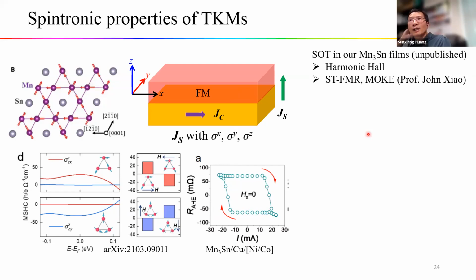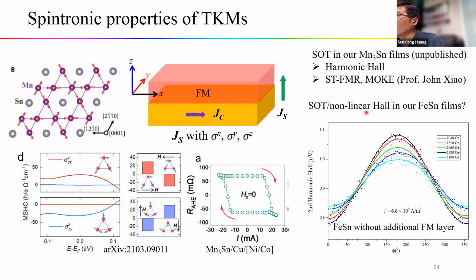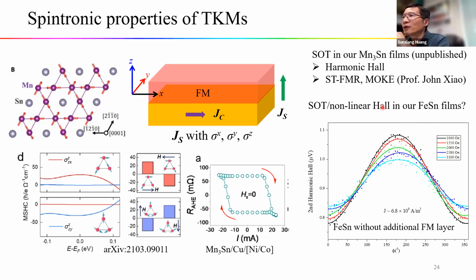We also have observed many interesting features in this material. Unfortunately, I'm collaborating with Professor Xiao, and I don't have much to discuss today. But another thing I'd like to discuss is that we recently observed a very interesting second harmonic Hall signal in these iron-tin films, which are antiferromagnetic. By applying a current density of around 7 to 10 times 10^9 ampere per meter squared, we observe a relatively large second harmonic Hall signal, which depends on the magnetic field. We are not sure where it comes from: it could be spin torque, magnon scattering, or some nonlinear Hall effect due to Weyl fermions. We still don't know yet, but it seems a very interesting topic to move forward.